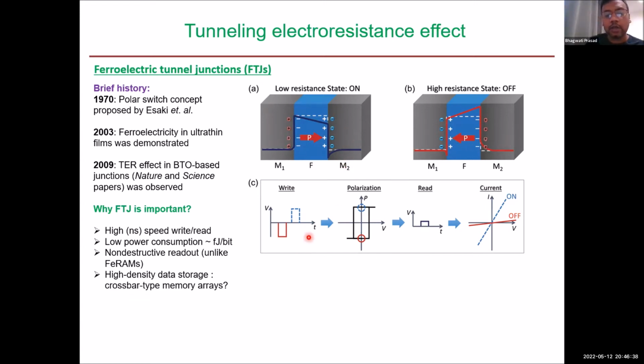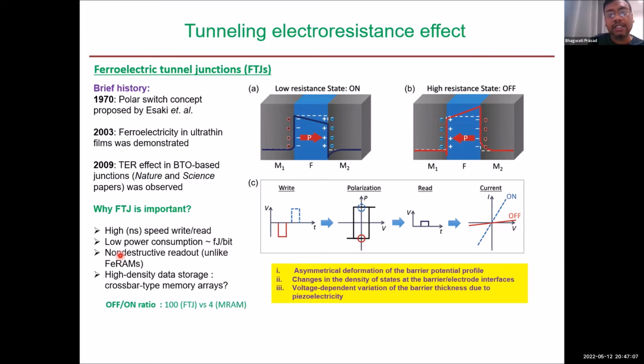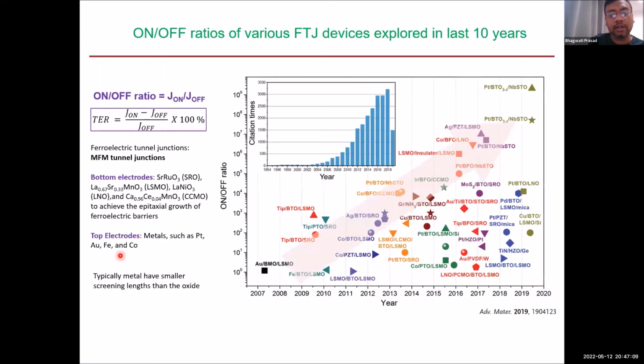Typically, you apply a large voltage to switch the ferroelectric in one direction or the other, and that way you have different barrier heights. Then you apply a small voltage and you can read this. FTJ is important because you can do very fast reads, nanoseconds. It's a low power consumption device with non-destructive readout, and one can think of high density data storage with that.